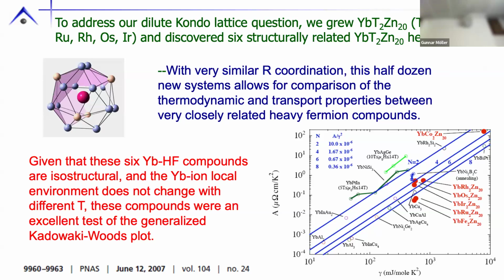So what do you take N as being physically? Oh, okay. So for a doublet cerium, your gamma TK is R log 2. Yeah. It's the amount of entropy you're hybridizing away. Here, it would be R log 8. So I'm actually having my full Hund's rule ground state multiplet being hybridized away.